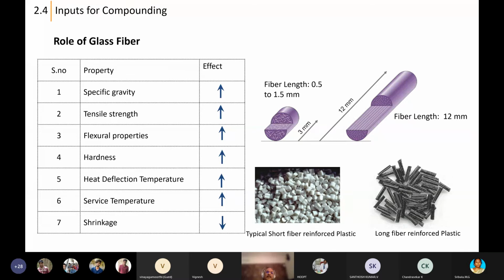So in overall effect, when you add glass fiber, the specific gravity will go up because the specific gravity of glass is higher than that of the plastic. Depending upon the percentage, specific gravity will go up. A plain nylon will have 1.14 density. When you fill it with 30% glass fiber, it will go to 1.36. Tensile strength will go up. Flexural properties do go up. Hardness increases. Heat deflection temperature and service temperature increase. Shrinkage comes down. This is important.